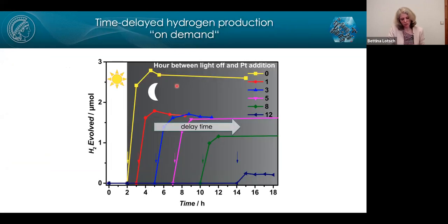So basically, we are increasing the time delay and add the co-catalyst after, you know, hours of turning off the light. And then you can see we have a substantial delay in hydrogen evolution. This is basically all very unoptimized data, but we can also clearly see that hydrogen is also evolved after, you know, 7 hours, 10 hours, and so forth. So we can really include a substantial time delay between light excitation and dark photocatalysis.